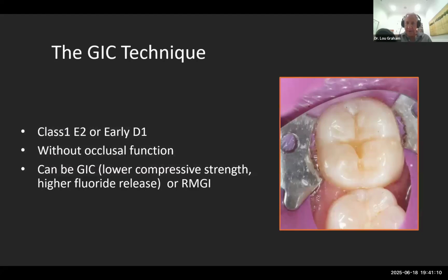So here's the technique. Becky comes in, she's got an early, I'd say D1 lesion. I could prepare this, and by using articulating paper first, just to establish her baseline of occlusion, I knew that she would not be in function with this final restoration. So higher caries risk, she's not going to be in function on this small preparation. My treatment of choice was a glass ionomer. Whether you want to use a resin modified or a pure self-cure glass ionomer, that's up to you. A pure glass ionomer is a bulk fill, self-curing, with lower compressive strength and higher fluoride release versus the traditional resin modified glass ionomer. And we'll touch on this more.